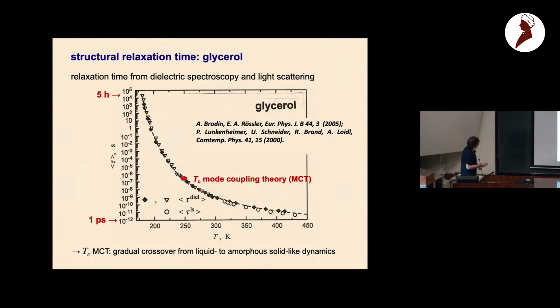First of all, glass-forming liquids. I always like this plot here for glycerol. This is the relaxation time from different experimental techniques, dielectric spectroscopy and light scattering. On the y-axis, it varies from 1 picosecond to 5 hours. There's one temperature that I've marked here, the mode coupling theory temperature, which marks the region where one has a gradual crossover from a liquid to an amorphous solid-like dynamics.